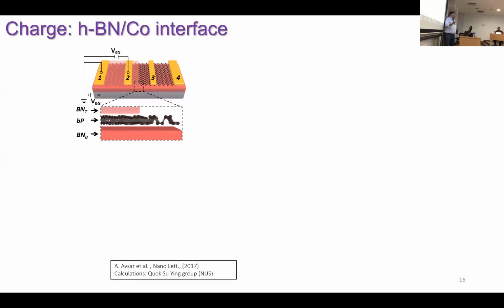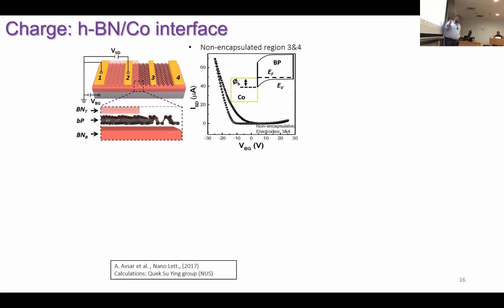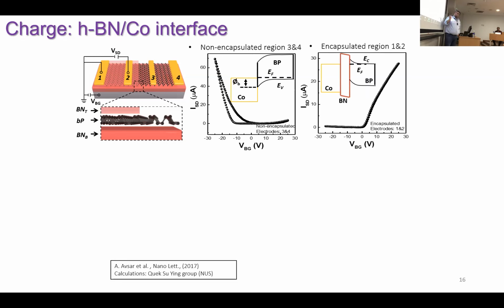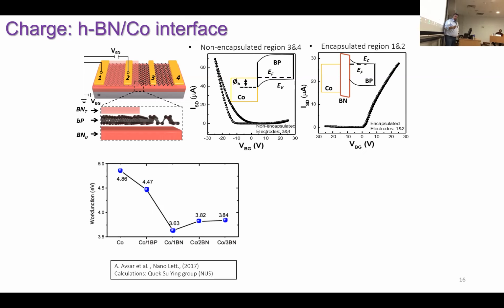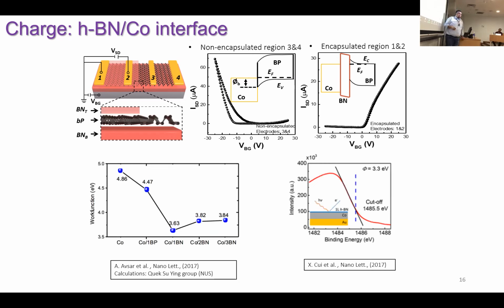So we started with a very quick charge transport characterization. We also saw some interesting physics here. You can already see that some parts of the devices are encapsulated with hBN, and some parts are not, so they are directly contacted with cobalt. This is the area where there is no hBN encapsulation, and the charge transport looks like a regular p-type transistor. Whenever you put a thin layer of hBN, the device changes from p-type to n-type transistor behavior by just inserting a very thin layer of hBN. So we were curious why this is happening. Basically, the work function is modified with the insertion of a thin layer of hBN.